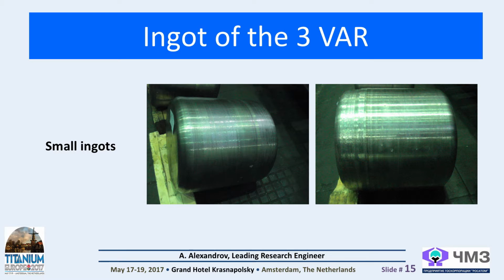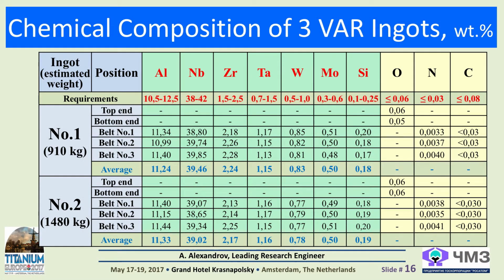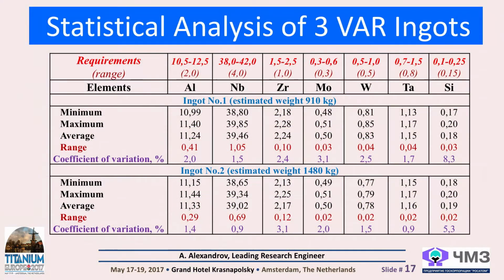To determine the chemical composition of the ingots, the samples were taken after removal of an external layer of the metal, in the form of chips from 3 belts of a lateral surface, from the ends and the middle of an ingot, and in the form of compact metal from the ingot ends to determine the content of oxygen and hydrogen. Table 1 shows the results of chemical analysis of the sample. Of course, there are many numbers, but the main conclusion is that the ingot corresponded to the established requirements, there in the second line. At the same time, it was possible to fulfill the strict requirement for the oxygen content, 0.06. That's maybe the main conclusion from this work, because it was really very difficult to fulfill it.